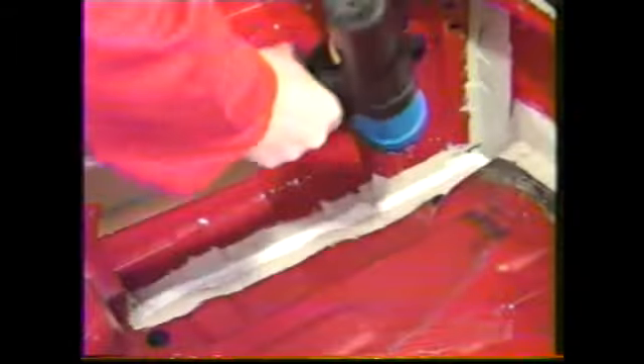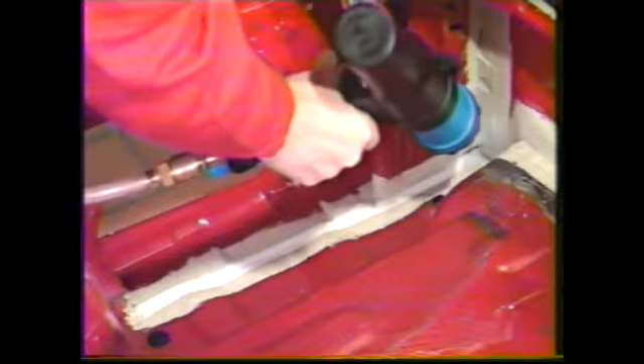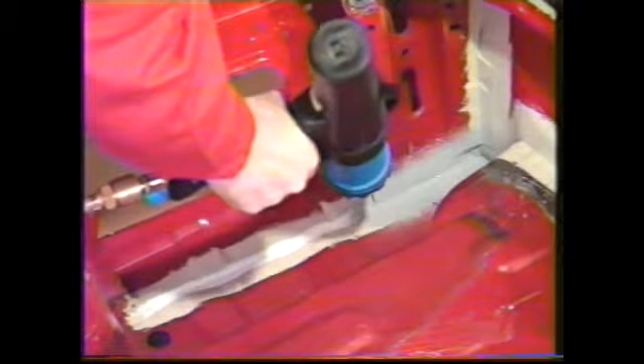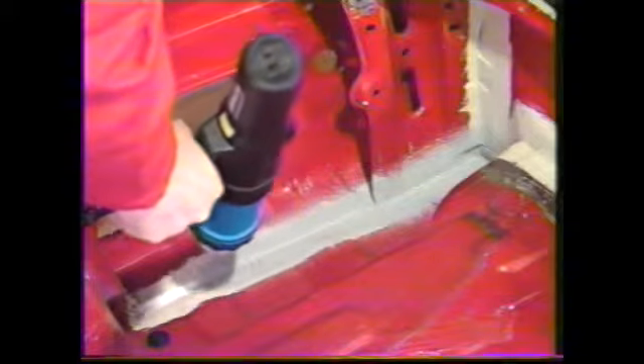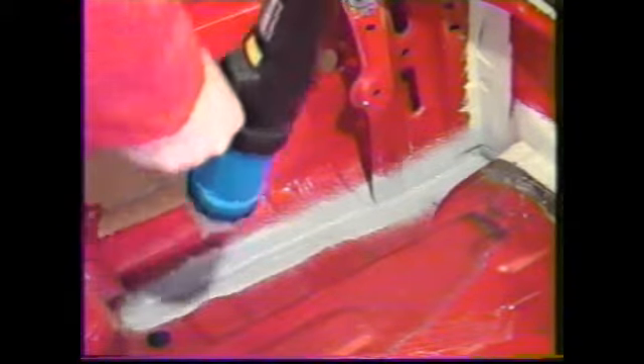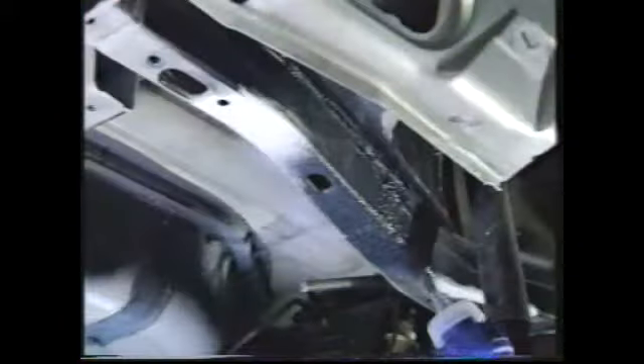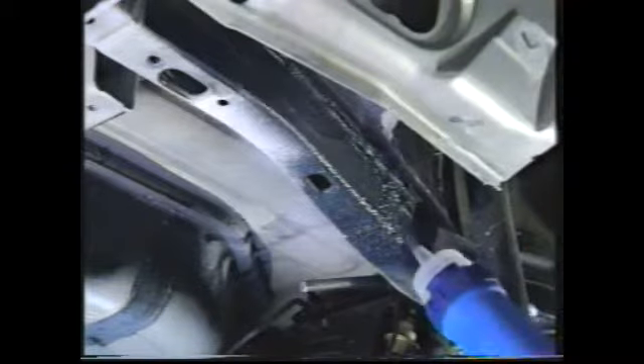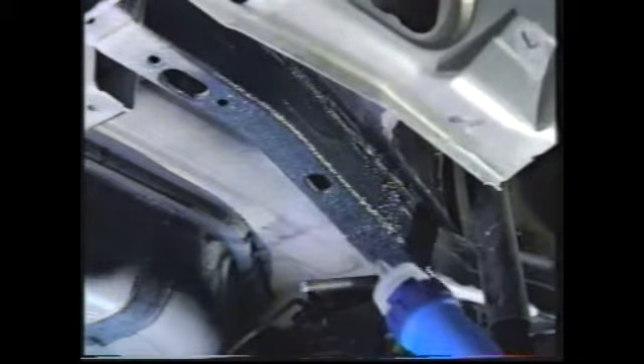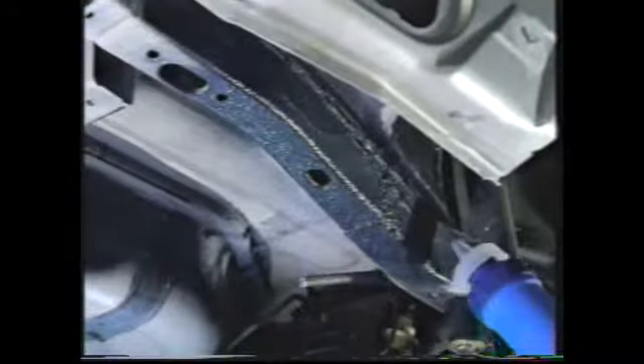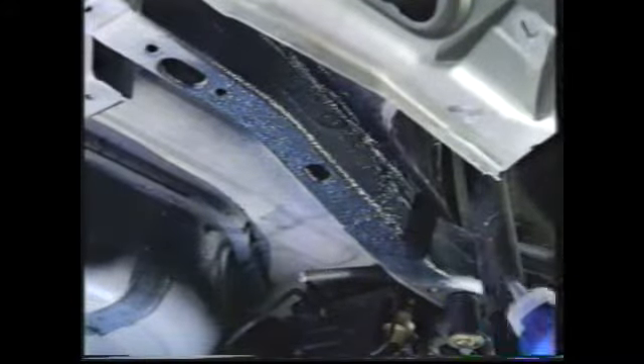Its remarkably good adhesion to all normal car substrates and to many plastics makes Terrastat 9320 a thoroughly reliable seam sealant. It displays, moreover, good temperature resistance from -40 to +90 degrees centigrade, and for short spells up to 130 degrees centigrade, and excellent ultraviolet resistance.